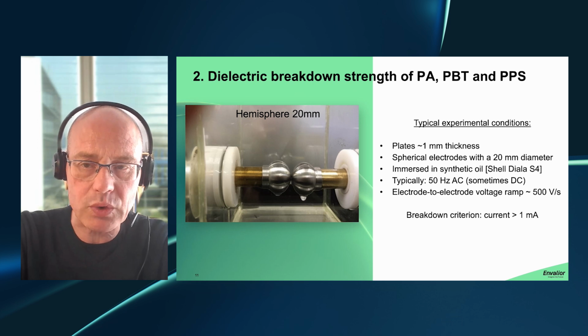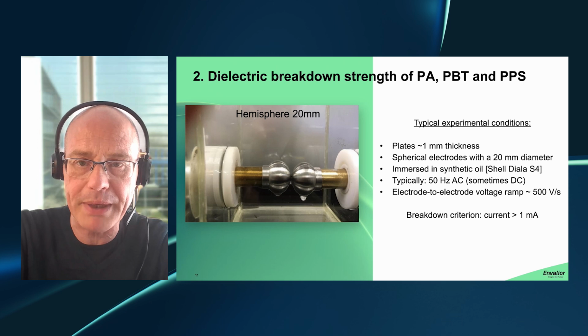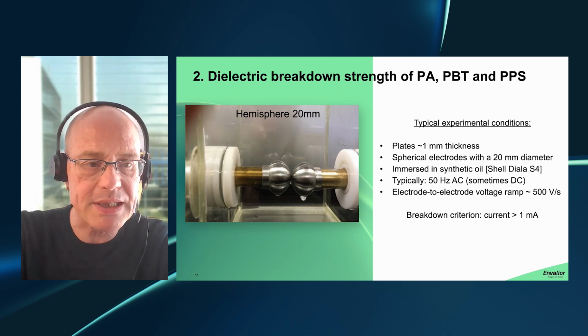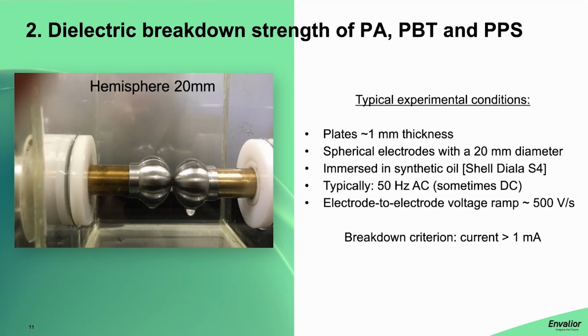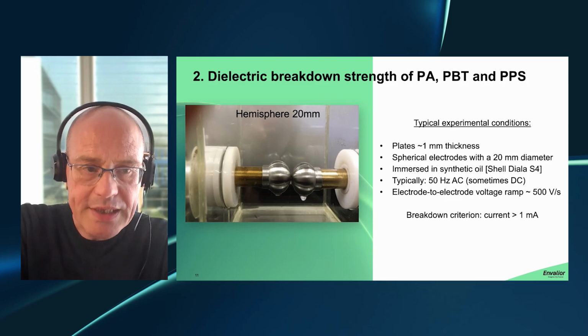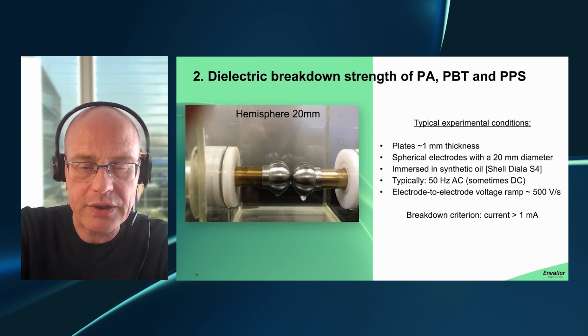And then in between these electrodes, and that is not shown here, you place a plate of your material under test. Typical thickness is 1 millimeter, but you can basically put in whatever you like. And then this whole setup is immersed in oil to avoid air breakdown near the electrodes here. And then you apply your AC or DC voltage, and you raise the voltage till the sample breaks down. Breakdown means till the sample conducts a current of more than 1 milliamp. And then the outcome of this test is your breakdown voltage or electric field in kilovolts per millimeter of plate thickness.